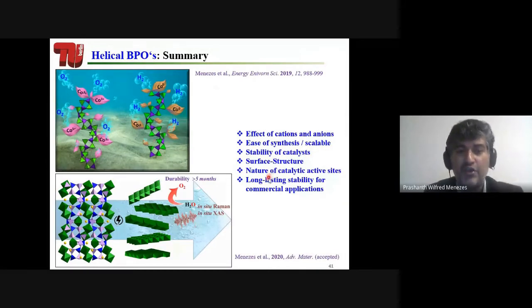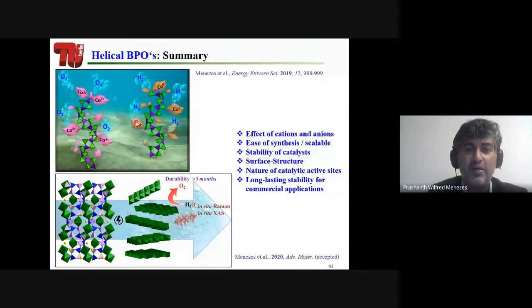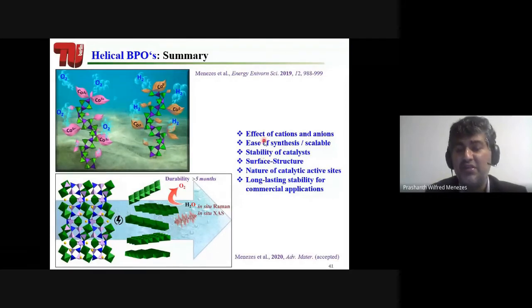Okay, to cut the story short, I already showed you that we had made such an efficient system with a very diverse structural aspect. And this is one of the other reports which we just published in Advanced Materials. This is similar to cobalt. We also made manganese, similar structure, and it also shows some completely different structure. And we could use this material for 5 months of stability. So this is really good.